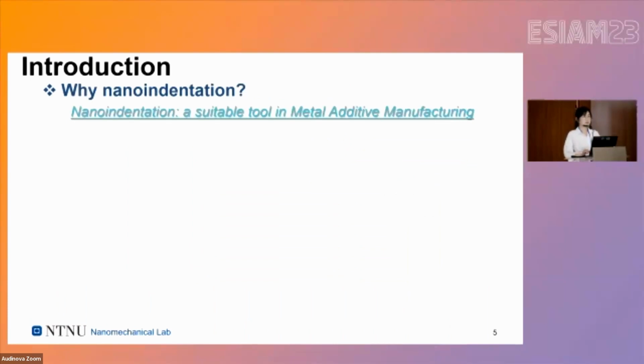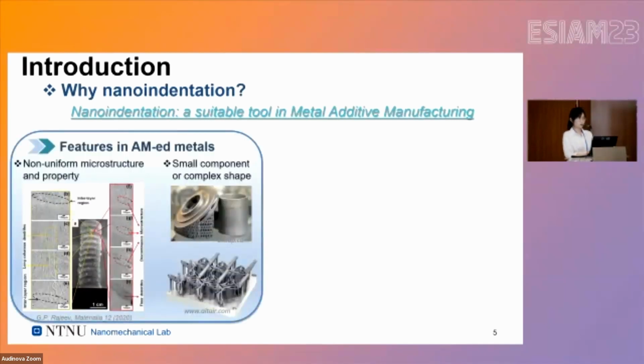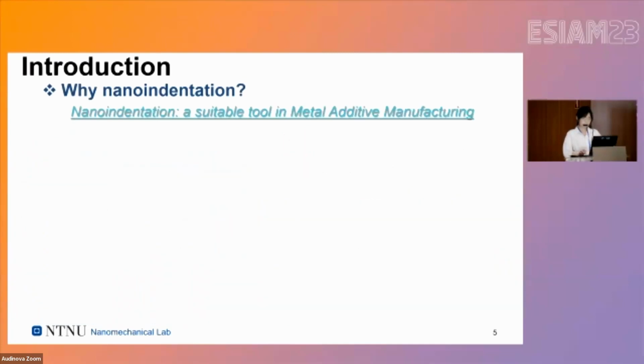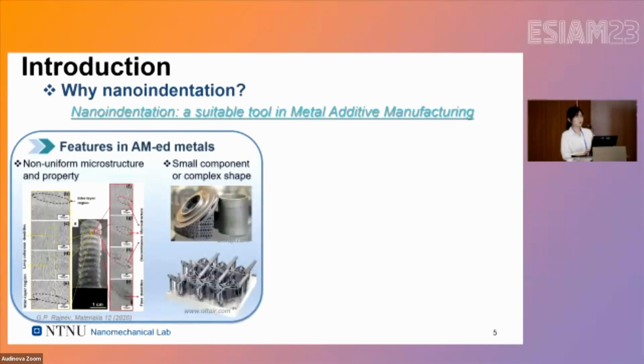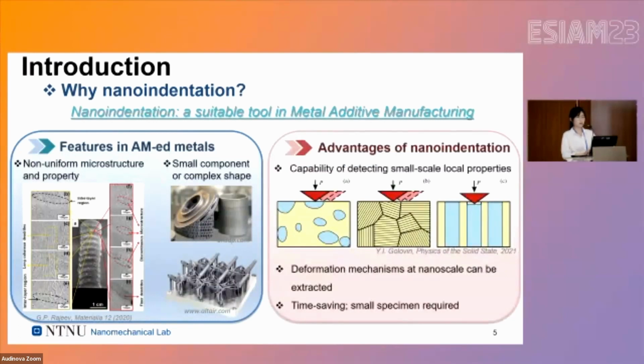Actually, in most of the research, conventional testing methods such as tension and compression have been widely used. But why do we use nanoindentation in metal additive manufacturing? The first reason is the features of additively manufactured materials. For example, for non-uniform microstructure and properties, and also for small components or complex shapes, the conventional testing methods are not applicable anymore. On the other side, nanoindentation has its own advantages. It can not only obtain small-scale local properties, but also the deformation mechanisms at nanoscale. Furthermore, nanoindentation is a time-saving method, and only very small specimens are required during the tests.